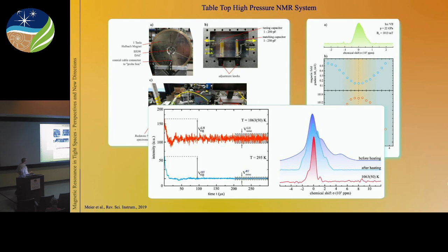And here on the right-hand side, you can see actual resonance spectra. So this is before heating. This has been done while we have been heating. So the whole experiment basically did not last longer than approximately 30 seconds, because heating for such a long time is actually quite dangerous for diamonds, which we unfortunately found out in the next experiment, because then the diamonds basically cracked open.